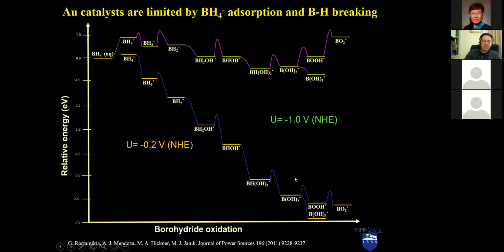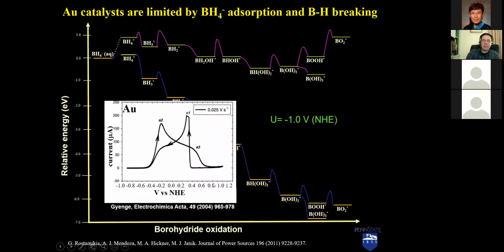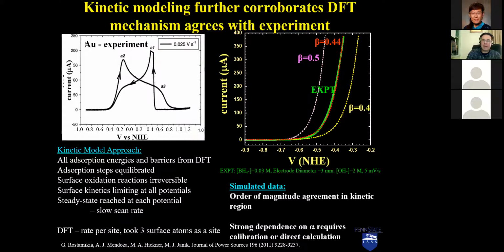This is all on the gold surface. This agreed pretty well with what's seen experimentally. No current at -1 volt, where some of these barriers are pretty high, pretty good current density around 0.2. We can actually take every one of these barriers, put it into a microkinetic model and predict the current as a function of voltage. And we agreed pretty well with experiment doing that. There are some assumptions we had to make about transfer coefficient. I can get those lines to line up perfectly if I make the right assumptions.